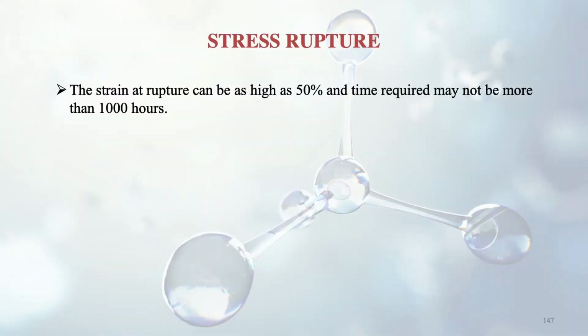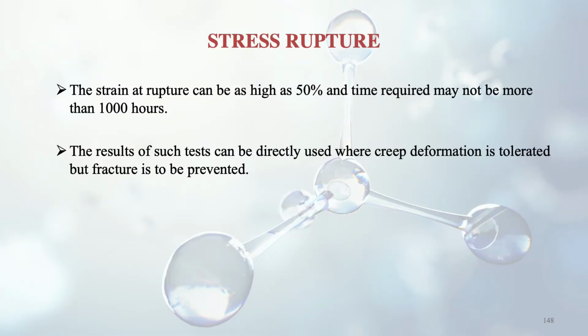The strain at rupture can be as high as 50%. So there can be strain of 50%, up to the level of 50% in the material, and time required may not be more than 1000 hours. So we see here that the time has lessened, so we can perform this test much easily as compared to the creep test. It was taking around 10,000 hours earlier. The results of such tests can be directly used where creep deformation is tolerated but fracture is to be prevented.